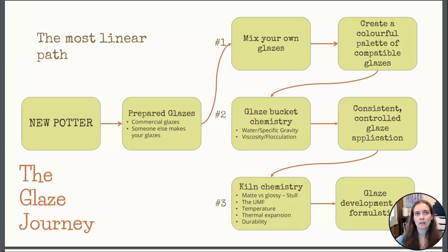And then we learned how to take any glaze and change the color of the glaze. That's the first step to glaze testing, where you're starting to change your recipes and make them a little bit your own, so that you're not just using the same recipe that everyone else is using. You can take a recipe that has 2% cobalt, and you could test it with 1% cobalt. Cobalt usually makes blue, so if you reduce it from 2% to 1%, you would maybe get a paler blue or a less intense blue color.